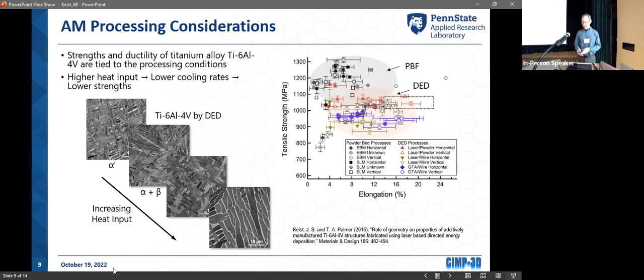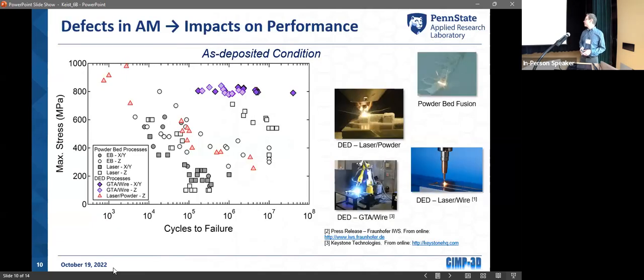And that brings up another important thing in additive, and that's defects. A lot of these processes are time consuming. This upper right is a powder bed fusion. You're doing a layer by layer process, typically 30 microns per layer. It may take 10 minutes to do that 30 micron layer. Imagine you're building a part that's over 100 millimeters in height. It could take weeks to build that part within a powder bed system. In that time of weeks that you're building, a lot of things can happen, including defects.